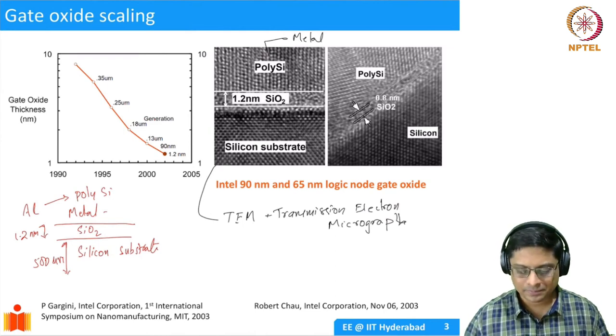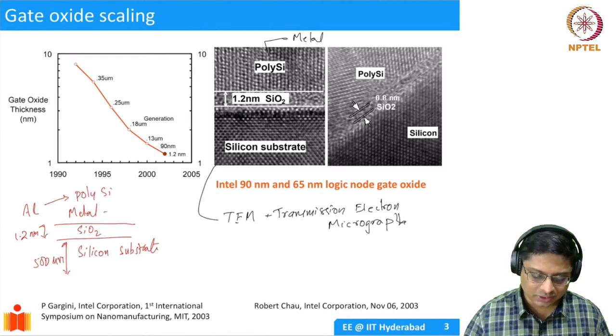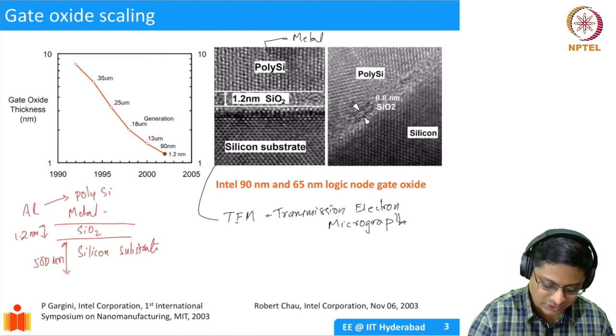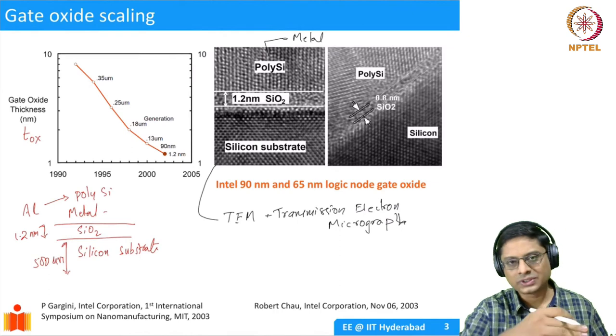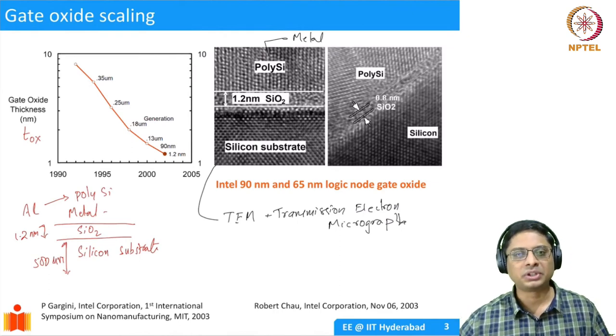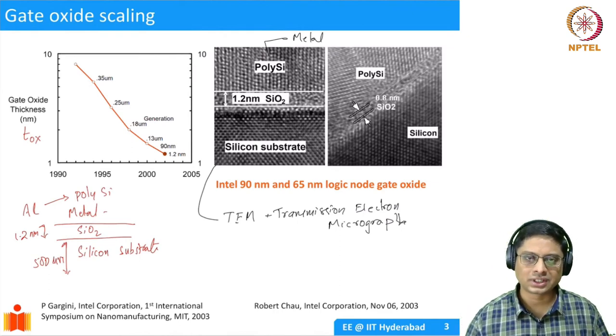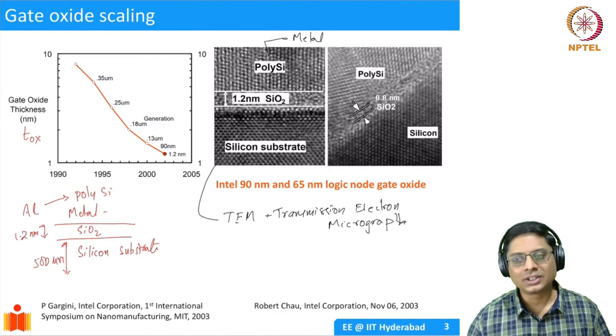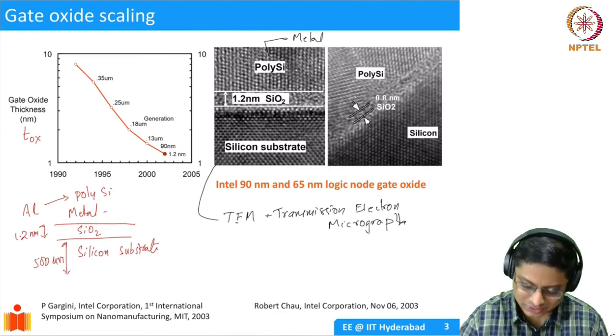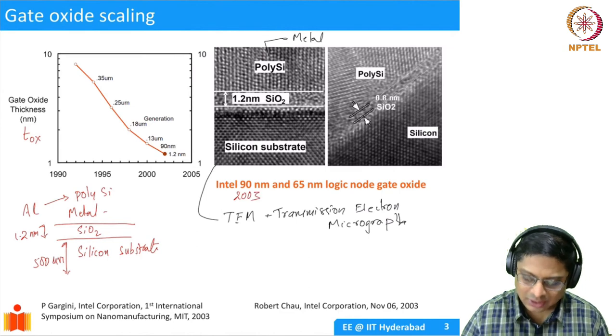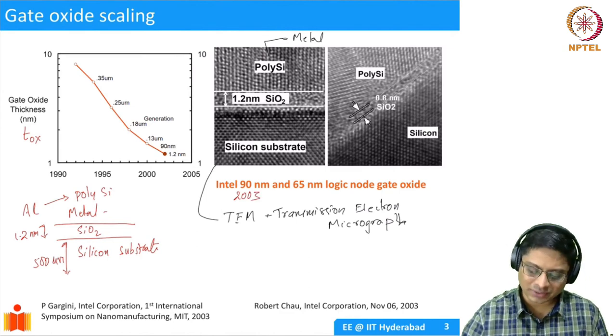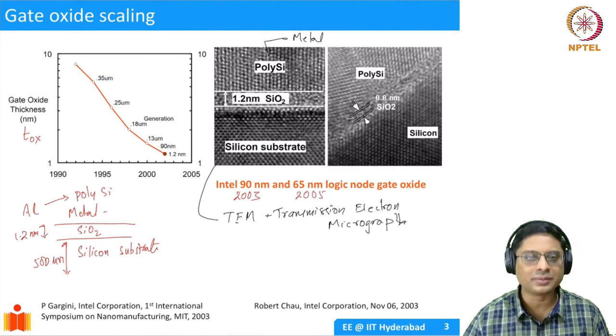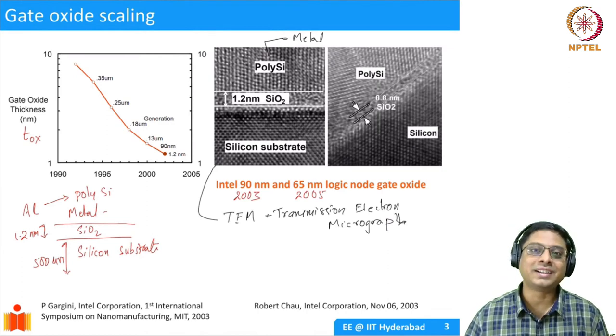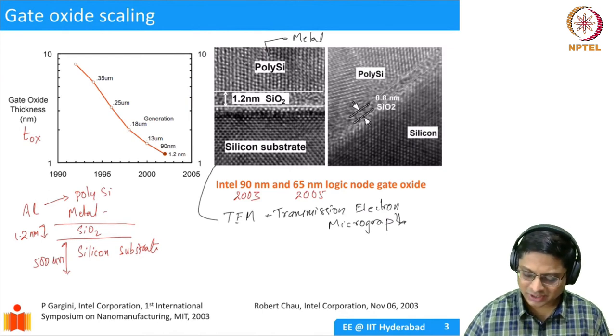And you see this TOX reduced. This is TOX. TOX was scaling from 10 nanometers to 1.2 nanometers. This was in 2003, I would say, 90 nanometer technology. By the time 2005 came, there was 65 nanometer technology, where the thickness of the silicon dioxide became 0.8 nanometers. These are images taken from a presentation by Robert Chau.